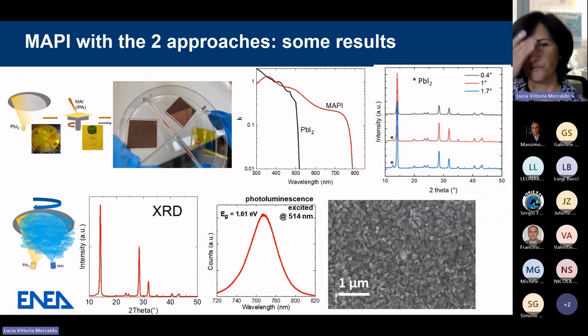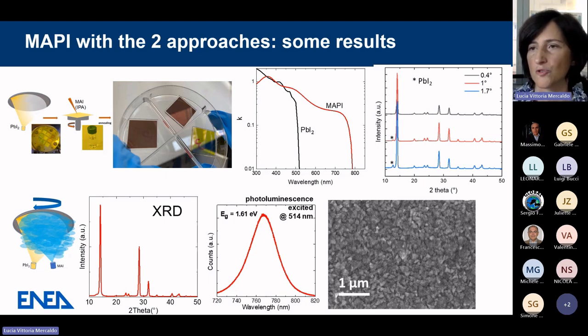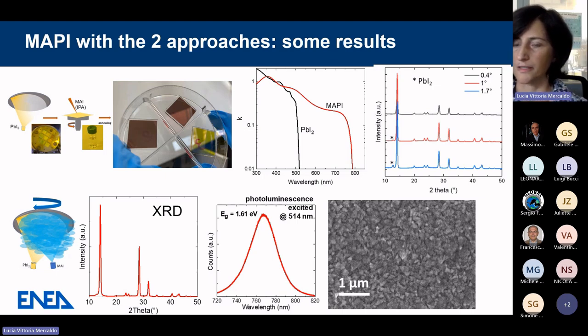And here I'm showing just a few figures related to the optimized samples, so some results on the films. On the top line, we can see results related to the two-step hybrid approach, and the bottom line, the co-evaporation approach. We see some properties like photoluminescence, XRD, and optical results. Also, just to give you an idea of the facilities that we have here in our lab, an SEM micrograph here.